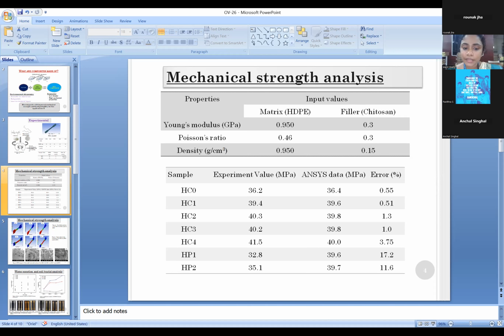In the tensile strength data, when we are adding palm oil, the unsaturated centers of palm oil consume the dicumyl peroxide, which I am adding as the free radical initiator. It is consuming the unsaturated centers of palm oil. So there is little interaction between the filler and the matrix. The interaction between chitosan and HDPE is minimized when palm oil is added. So it is showing a high error percentage in the ANSYS data, as well as when I am comparing it with the theoretical values.